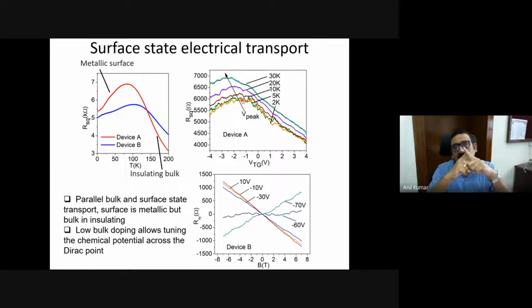Exactly at the Dirac cone, which is the charge neutrality point, the density of states is minimum. When the density of states is minimum, the resistance is maximum. So that is the reason it is going through a maximum. Then you may ask a question: how do I know this is an N-type region and this is a P-type region? We do Hall effect measurement. This is another device, for example, where we are applying back gate voltage, and there we vary the applied magnetic field at different gate voltages.